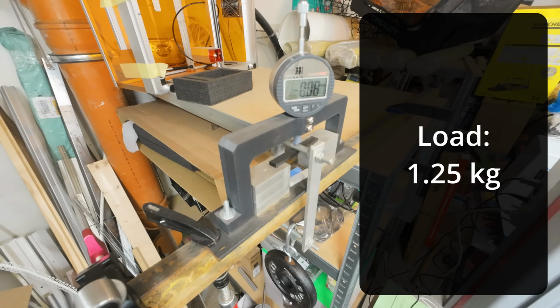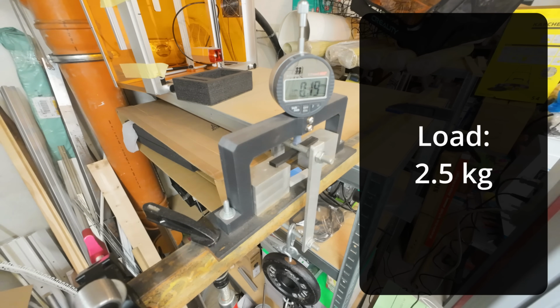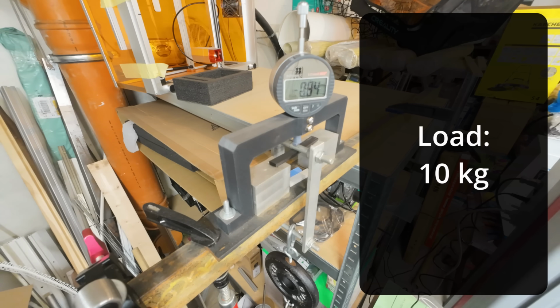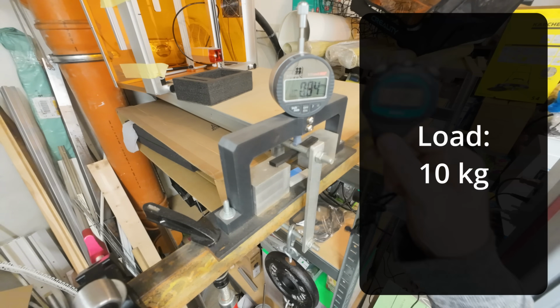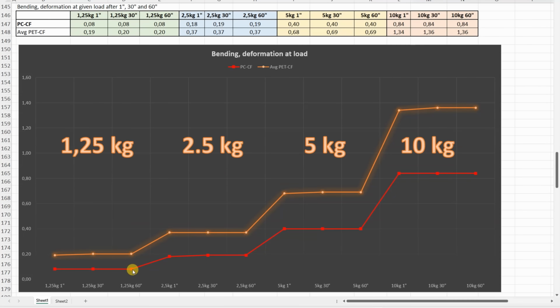3-point bending test. Distance between supports is 50 mm. And I'm placing these loads and I'm measuring the deformation after 1, 30 and 60 seconds. Currently under 10 kilograms and no additional deformation during this 1 minute. Now this one is interesting. Not only can we see smaller deformation on this PCCF, but look at this. Under 10 kilograms, absolutely no additional deformation during that 1 minute. This is an extremely rare situation.